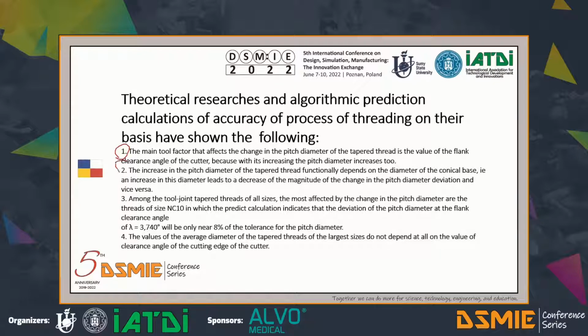The second, the increase in the pitch diameter of the taper thread functionally depends on the diameter of the conical base. An increase in this diameter leads to a decrease of the magnitude of the change in the pitch diameter deviation, and vice versa. The values of the average diameter, so the mean pitch diameter of the taper thread of the largest size, do not depend at all on the value of the clearance angle of the cutting edge of the cutter.